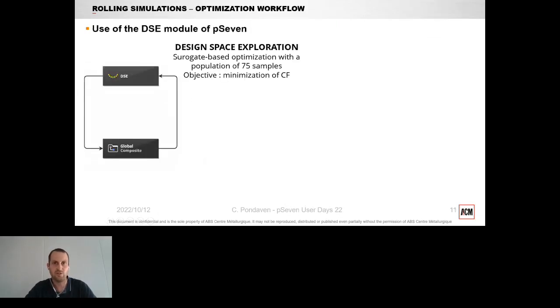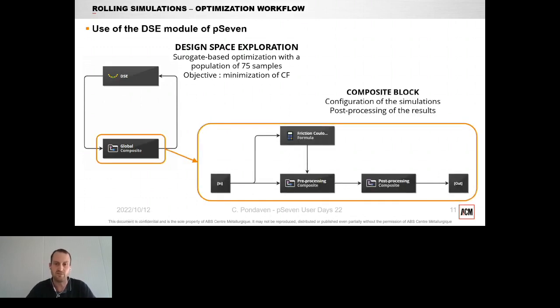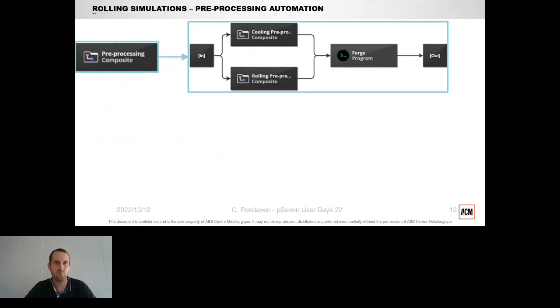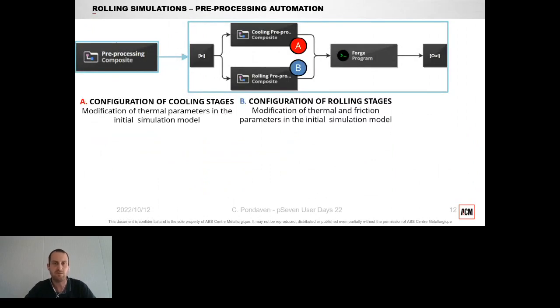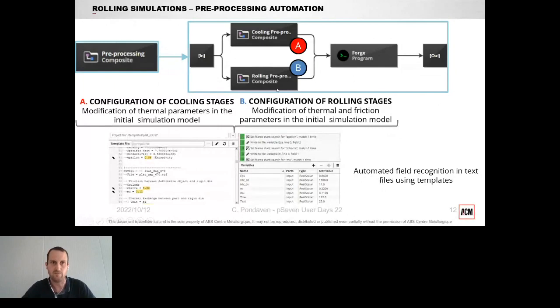To perform our optimization, we use a workflow constructed using the design space exploration with a surrogate-based optimization technique with a population of 75 samples, and the objective is the minimization of the cost function. We then have a composite block, which is composed of a pre-processing phase and a post-processing phase to compute the different results. During the pre-processing phase, we have 2 different types of blocks. One type of block configures the text file used in Forge to perform the calculation, the configuration file linked with cooling stages, and the configuration file used to configure the rolling steps.